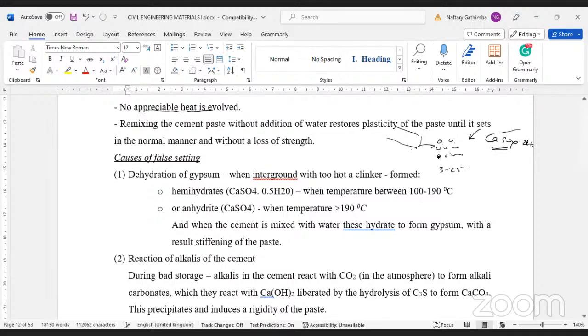But because the temperature is high when this clinker is exiting the kiln, if we do not give it time to cool down before we add gypsum, we may add this gypsum to clinker and some amount of water is lost. So our gypsum becomes dehydrated. So what happens? When we add water to that kind of cement, when we are mixing, it's going to take the water that is to be used. Remember the primary purpose of water is for the hydration process. So if this water is diminished before the hydration process occurs, your cement paste will harden. And this is why we say false setting will occur.